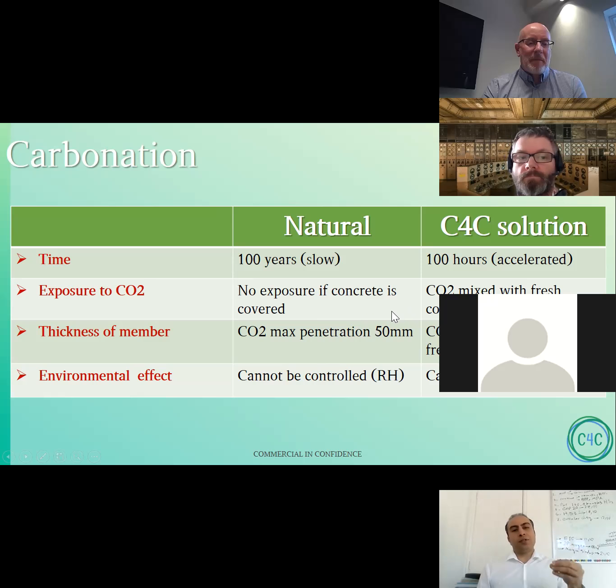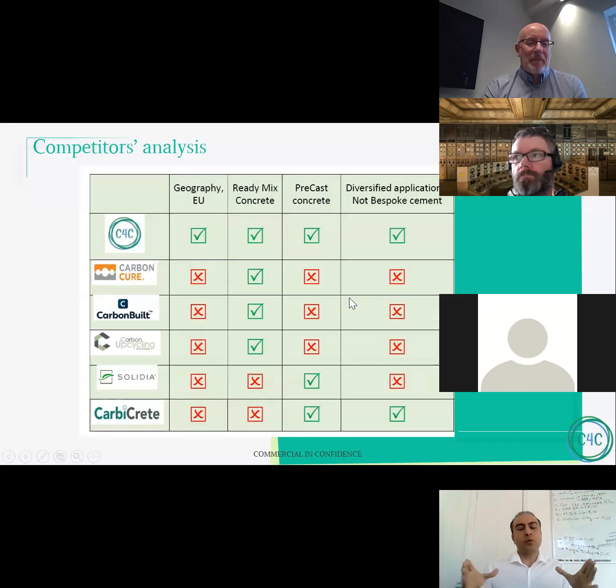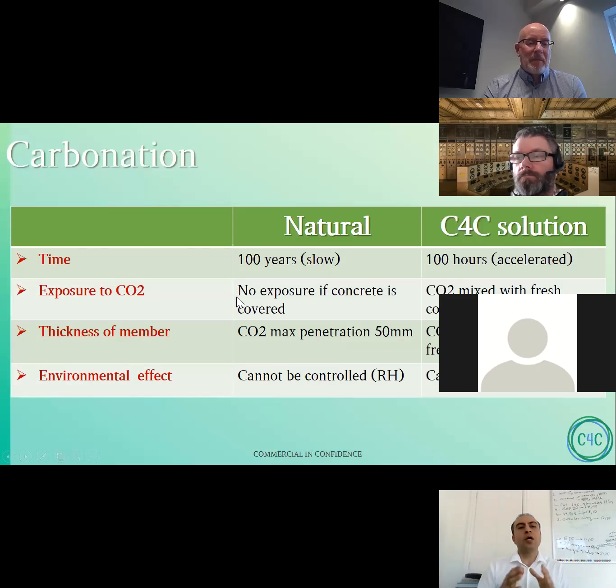In terms of thickness, the CO2 from the atmosphere is not able to penetrate more than 50 millimeters inside the concrete. However, because we are uniformly mixing CO2, CO2 is available at any depth of concrete. And finally, we need a specific temperature and relative humidity to enable and optimize this carbonation. It is not possible to control this carbonation for 100 years, but it is possible to control that for a period of 100 hours. Next page, please.